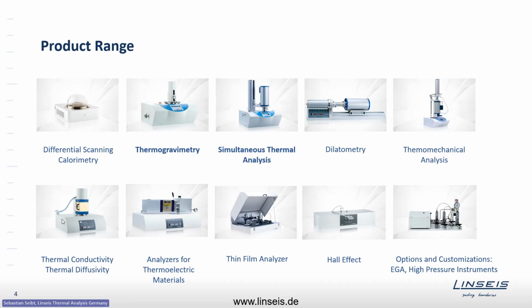On the lower line, you can see the instruments for thermal conductivity measurements, which is laser flash, heat flow meters, guarded heat flow or guarded hot plate instruments, hot wire instruments, many more. So a broad range for thermal conductivity. The same for thermoelectrics. We have a broad range of thermoelectric analyzers for measuring Seebeck coefficient, Hall coefficient, thermal conductivity, and electrical conductivity in combination. And of course, resistivity as well as conductivity. And the whole thing also for thin films, microchips, coatings, and that's the complete range we do.